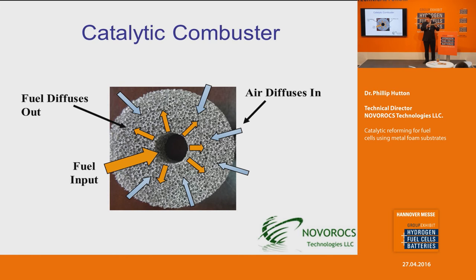In a catalytic combustor, similar to this, what this is, is a cylindrical metal foam that has an aperture in the middle, and it's surrounded by a mesh. And we flow propane through the middle. The propane diffuses out, and oxygen diffuses in. And they meet on the catalytic surface, and the oxygen combusts the propane without a flame. Once you get this up to temperature, around 350 degrees, as long as you're flowing propane in there, it maintains its temperature and it oxidizes, or combusts, all the propane without a flame. And since it's a low temperature combustion, you have much better emissions profile. No NOx coming out of it.